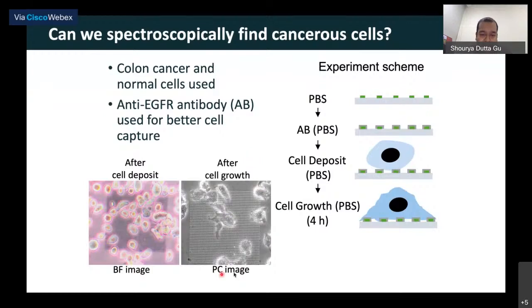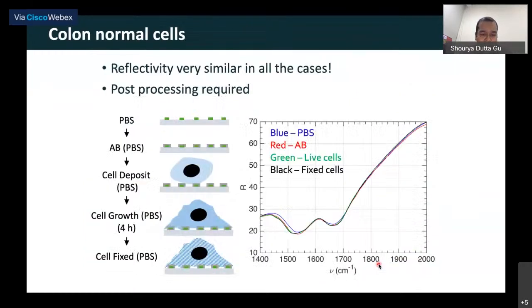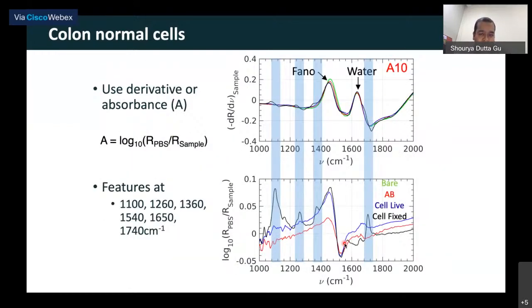Then you let the cells grow for 4 hours so that they spread out. If you compare these cells to this, you will see that they have this filopodia and they are spreading out. And then finally, you can fix the cells to look at them at a later time, right? So we measure the IR signature at all these time steps, and then we can plot them in a single plot as shown here. The vertical axis is reflectivity, and the horizontal axis is wave number. Now, if you notice, there's not a major change, right? However, if you look at either the derivative or the absorbance, which is typically done in IR spectroscopy, we start seeing different features arising for different states. These are the features that we can use for identifying different kinds of cells.